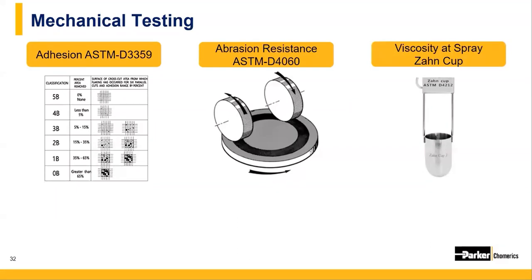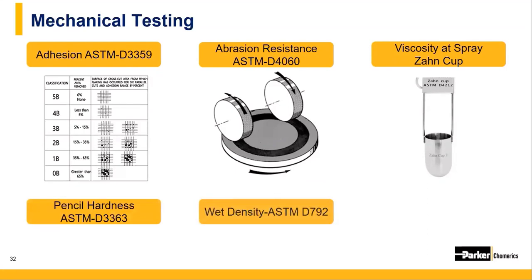Viscosity is measured using a Zahn cup. Each Zahn cup, numbers 1 through 5, has a different sized hole in the bottom for different thicknesses or viscosities of material. The cup is filled to the edge with a coating or paint, and the solution is then allowed to start flowing from the bottom of the cup. The time is measured until the steady stream of paint flowing from the hole is interrupted and is then recorded. The time is known as the efflux time. Other tests include pencil hardness, wet density measurement, and pot life, as we touched on earlier.